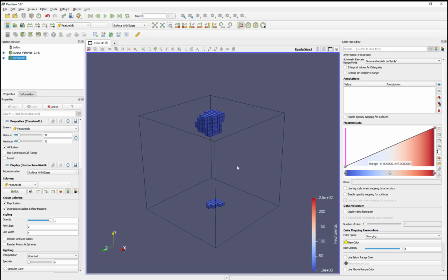Why this is important is because if we average FIPS over these volumes, we need to recognize that these should be separate grains, because the Y surface is now non-periodic. So what the algorithm does is it identifies all the grains split by the non-periodic face, and it essentially indexes them as new grains solely for the purpose of calculating and volume averaging FIPS.